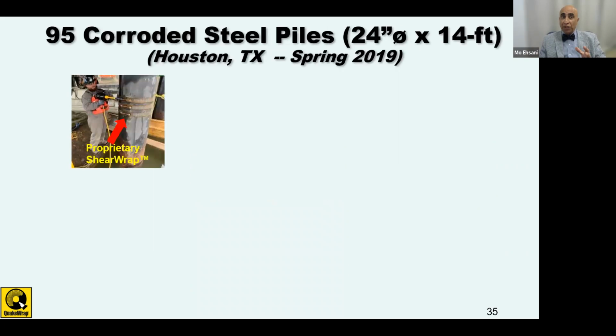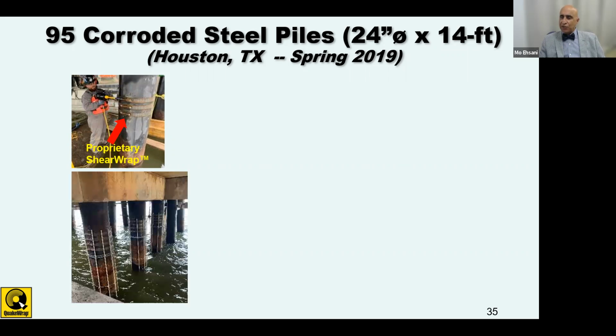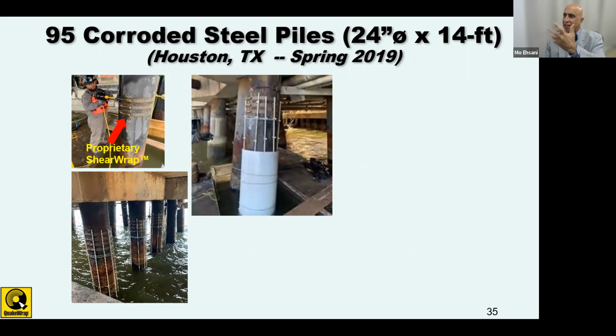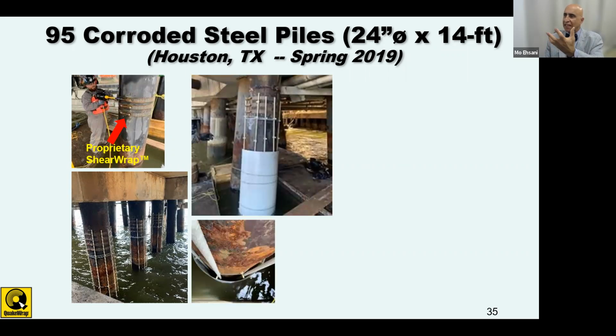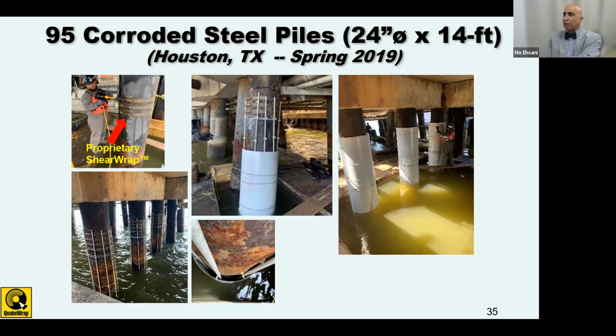But we do these also for strengthening, and there's something unique about this that I would like to point out to you here. In this case, for example, these are some steel 24-inch diameter piles for a client in Texas that, as you can see, we apply or provide some longitudinal rebars around there with those spaces, and then wrap the layers of laminate around it, and then the annular space gets filled with concrete or grout.